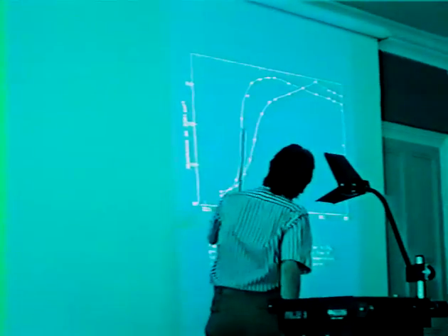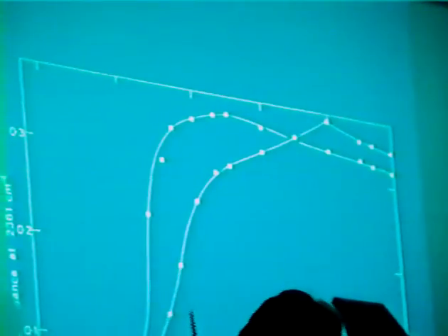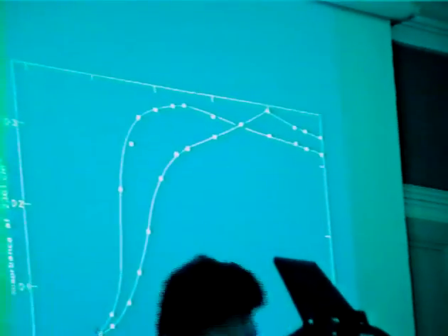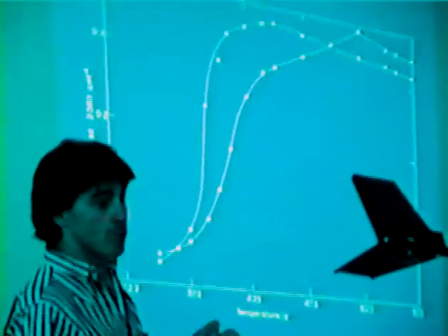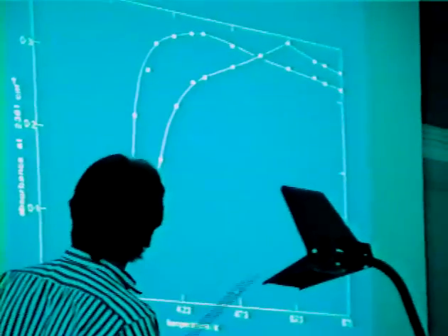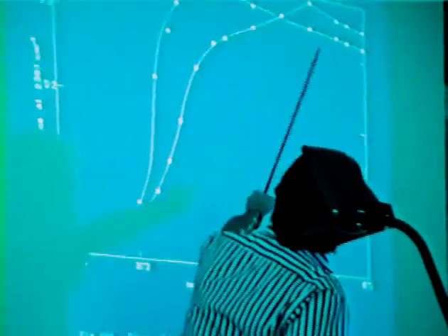So this is the initial run up here, and you can see that this is exhibiting a much less steep light-off than the re-reduced sample. In addition, as we approach 100% conversion on this plot of CO conversion against temperature, we get this sort of double maximum shape curve, which is also seen in the case of rhodium 100, for example. Whereas if you move to a much more close-packed crystal phase, such as rhodium 111, then this gives a similar type of light-off behaviour, with a rate temperature maximum, which we see here.